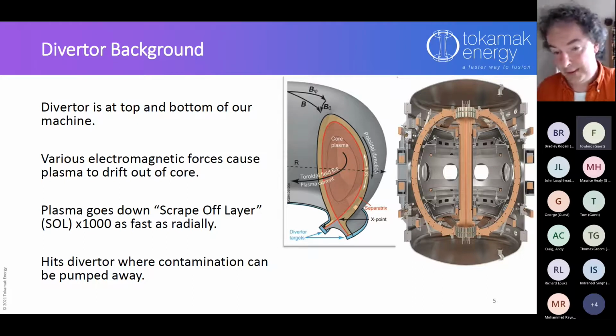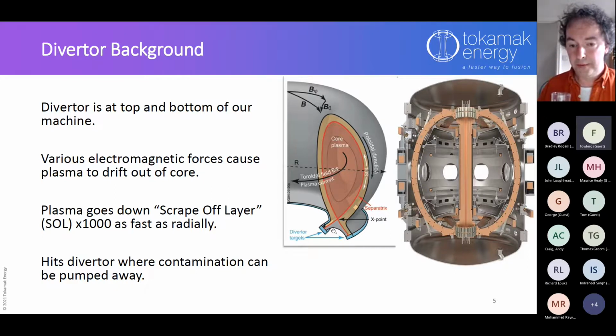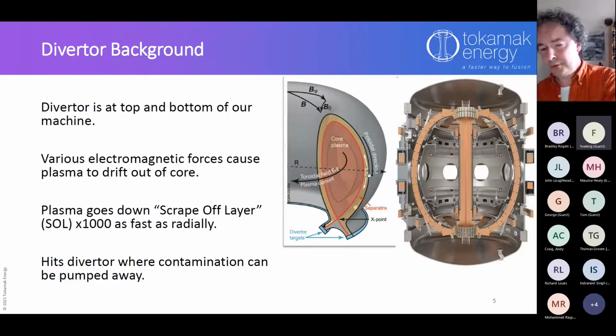They're still going to cause possibly melting, hopefully not melting, but possibly melting, sputtering and whatnot down here. We have various mechanisms to try and reduce the energy of these things, but these are more like sacrificial plates, and by putting pumping down here, you can pump away any debris that's being flung off your surface much more easily, and handle it down there, and it doesn't fly back up. So you've got a big vacuum pump down at the bottom here, trying to stop this stuff from floating back up and screwing up your core plasma. This thing is called the scrape off layer, because it scrapes off debris.